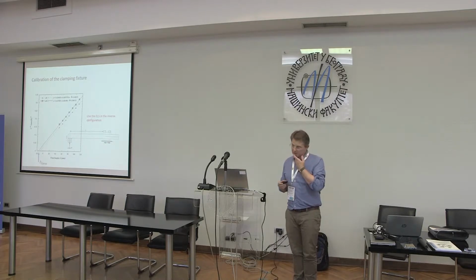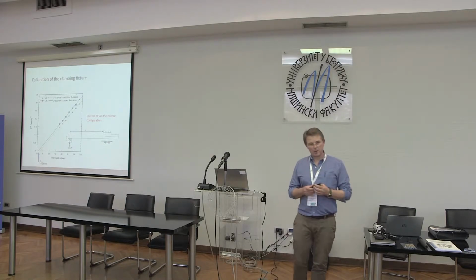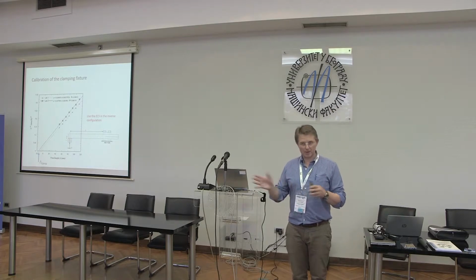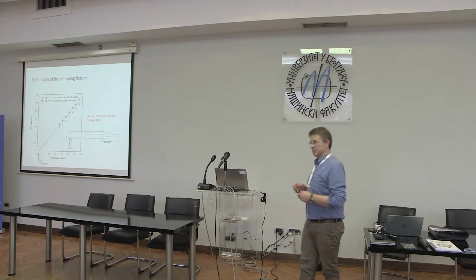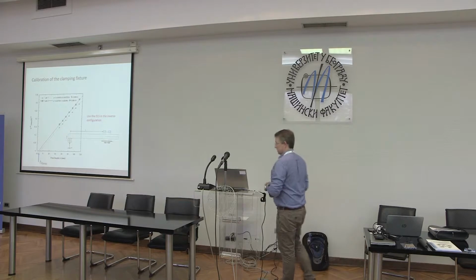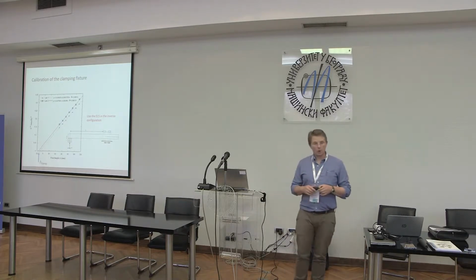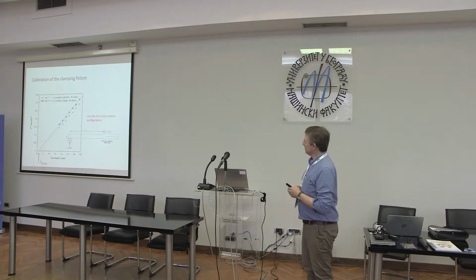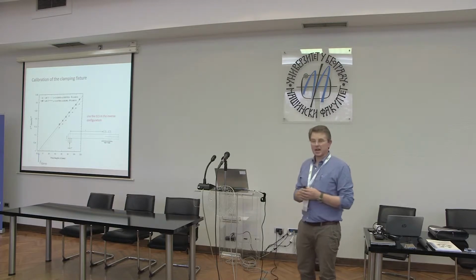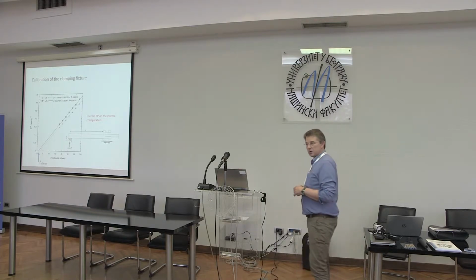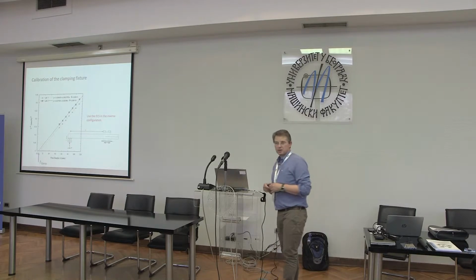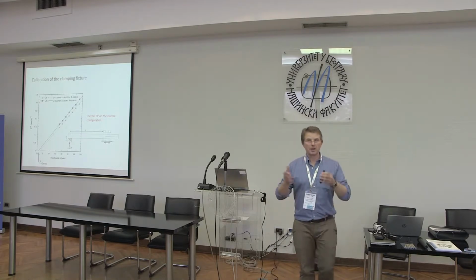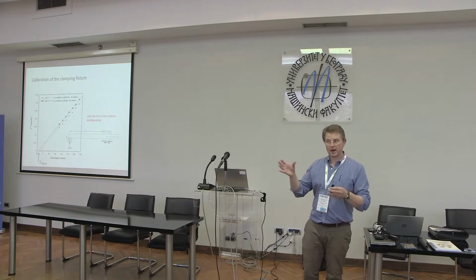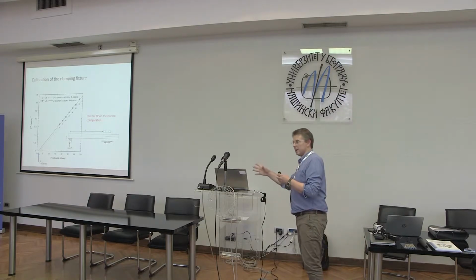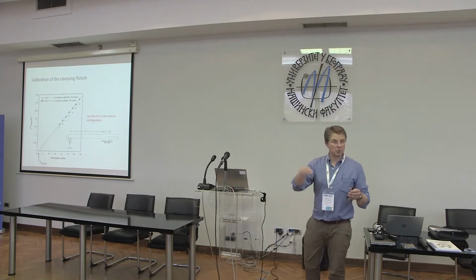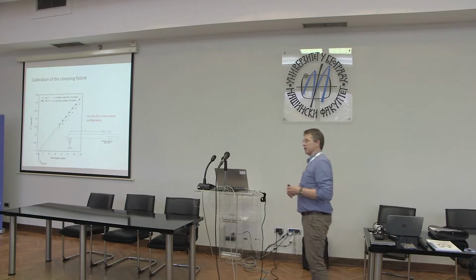So what we had to build into the method is a way of calibrating the experiment. So whenever someone is performing these sorts of experiments in their lab, they calibrate their apparatus on what we described as an inverse ELS clamp calibration. So what you do is you take a specimen which can be uncracked, or you can have it in the reverse format, so the crack is held completely in the clamp, which does then mean you can subsequently reverse it and do a fracture experiment on it.